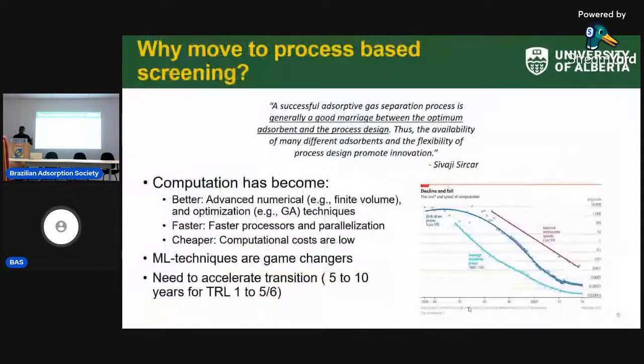If you go back to what Shivaji Sircar said, for those of you who do not know Shivaji Sircar, he is one of the most famous adsorption process engineers that came out of Air Products, with hundreds of patents, and essentially revolutionized oxygen VSA. He's no more, but he repeatedly mentioned that a successful gas separation process is generally a good marriage between the optimum adsorbent and the process design. So if you go to the industry, each process is tuned to the particular adsorbent. Even if you think about oxygen separation, if you use sodium X, calcium X, and lithium X, the process operations are completely different. Lithium X is a VPSA, sodium X is a PSA, calcium X is a VSA. All doing the same job, but depending on the adsorbent, I need to tune.